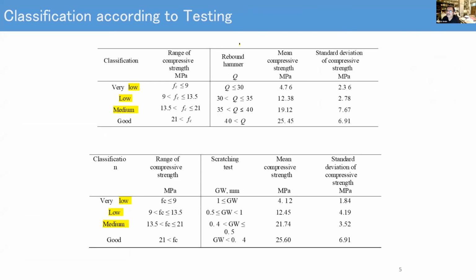So here, from our laboratory and field tests, it is found for the rebound quotient Q value, actually in our original Schmidt hammer we say R value, but here we go for Q, that means the mushroom head velocity ratio value, that if it is very low, less than 30, we have to say that it is very low strength, less than 9 MPa. If it is between 30 and 35, then the strength range will be indicative like this. And if it is between 35 and 40 Q, then it is indicative like this. Then if it is more than 40, it's a good concrete, meaning it has a characteristic strength greater than 21 MPa.